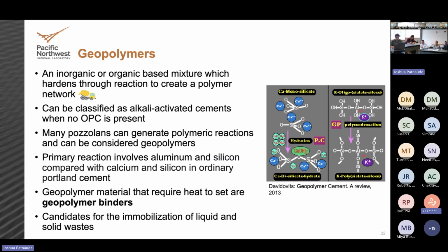Although in waste immobilization, and in my opinion, geopolymers in general, really is a gray area between what you call a hydraulic cement and what you call a geopolymer, because once you add in things like slag and fly ash to a geopolymer, you start to grow some traditional hydration products. It's not pure polymerization. So to me, geopolymer is just a broad term that people throw around if you don't have cement in your system.